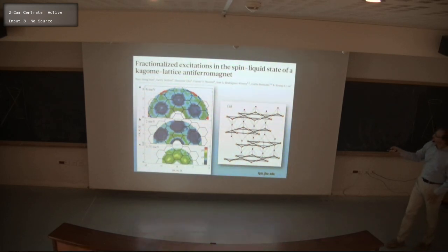And this is what you see. So here's the structure. Here is neutron scattering intensity as a function of momentum in the kagome layer. So it's a two-dimensional layer, so I've got 2 dimensions of momentum. And then I have 3 different energy transfer points, 7.5, 2, and 6 millielectron volts. And this is basically what comes out. It's really very strange. Honestly, this was the first time we'd seen anything like that. It also was almost one of the very first experiments we did on the instrument.